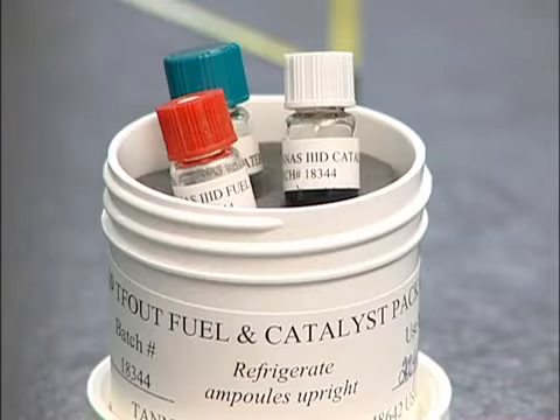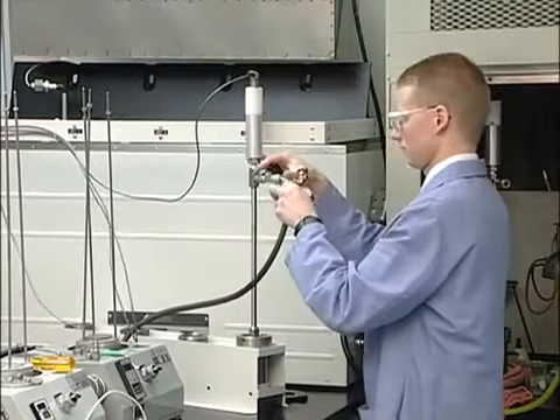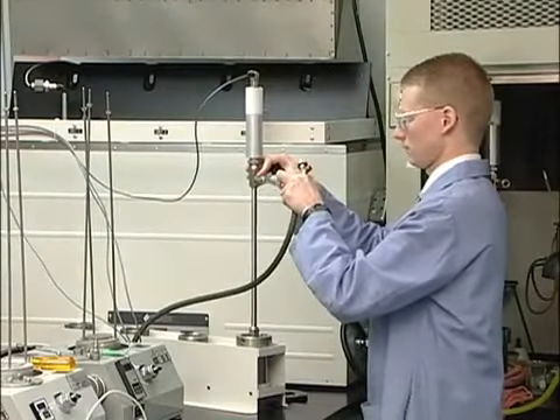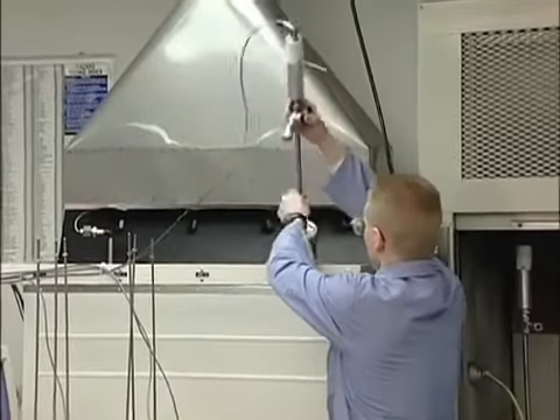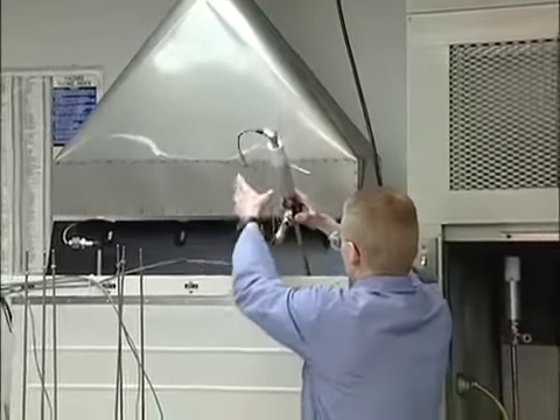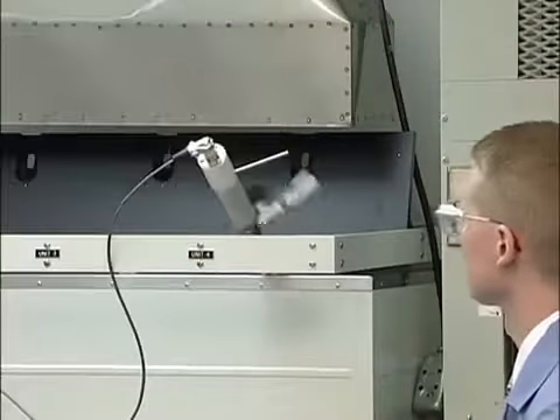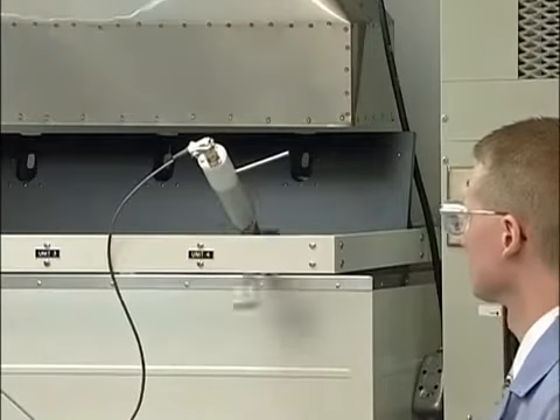For the TFOUT test, the catalysts represent different metals as well as degraded fuel and antifreeze contamination. A prepared sample consisting of 1.5 grams of the oil to be tested and the test catalysts is placed in a bomb which is pressurized to 90 psi with oxygen. The bomb is then placed in a hot oil bath at 160 degrees Celsius and rotated at 100 RPM.